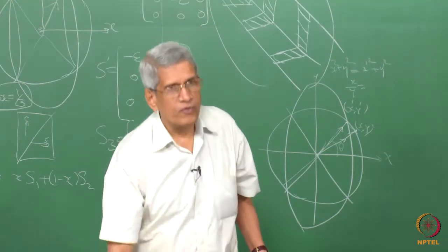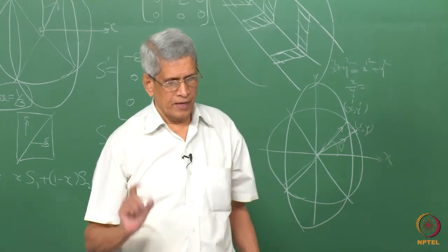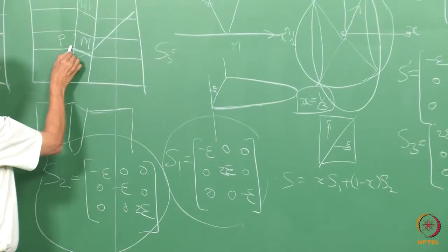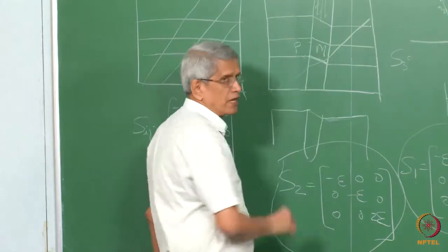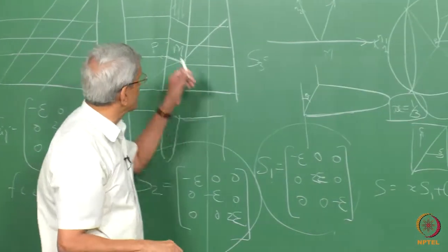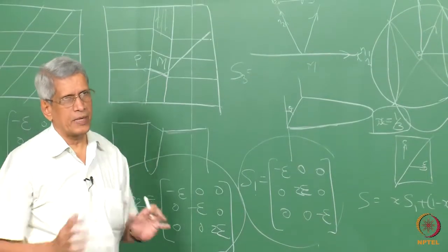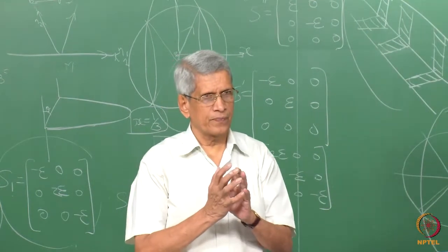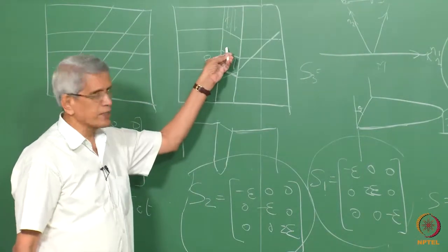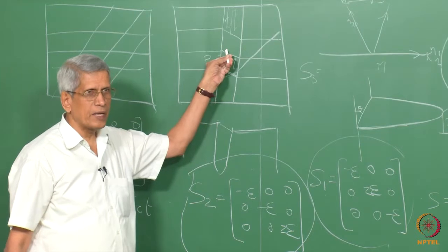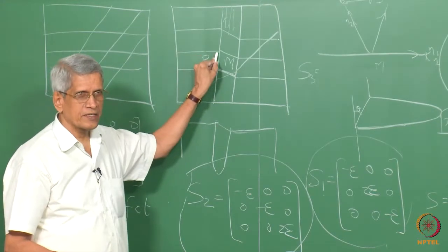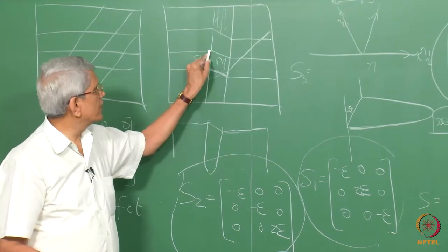Essentially, what we have to consider here is one of the experimental observations. Suppose we allow a region to transform like a normal diffusional transformation. Then after a deformation has taken place and shape changes have occurred, we allow some surface traction to bring it to the original shape. When we introduce it back, the strain will try to relax. So, the strain is accommodated in the matrix as well as the precipitate, whereas here that does not happen.